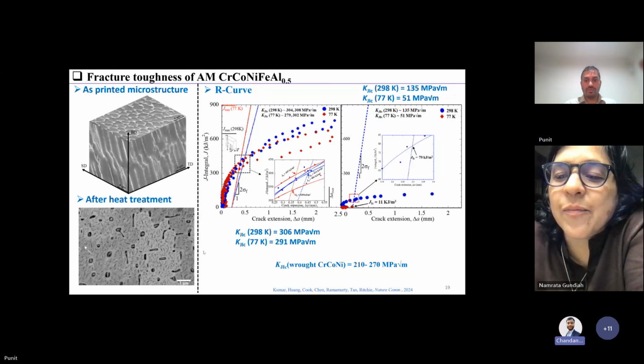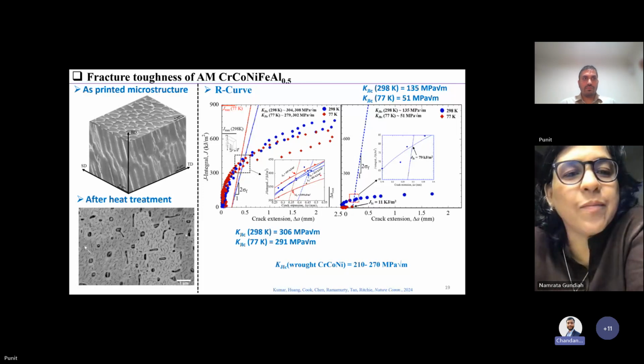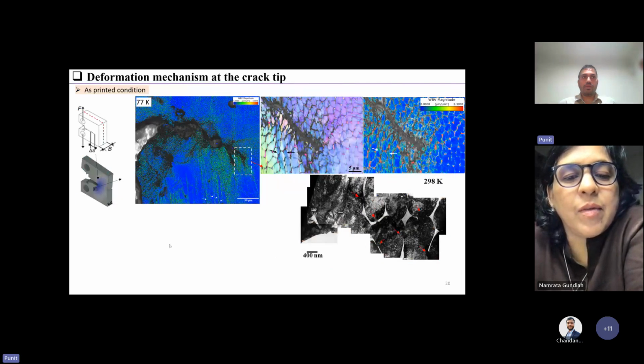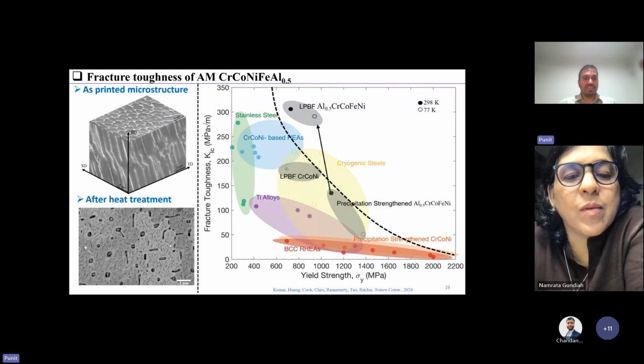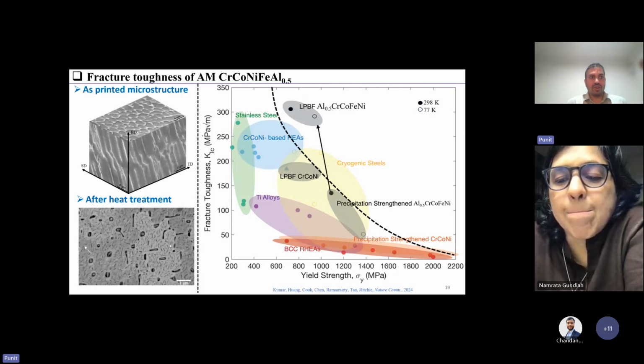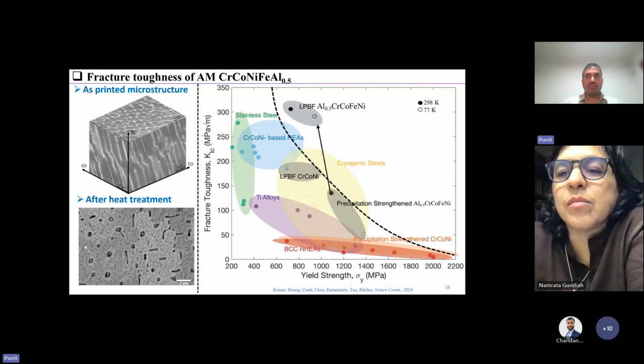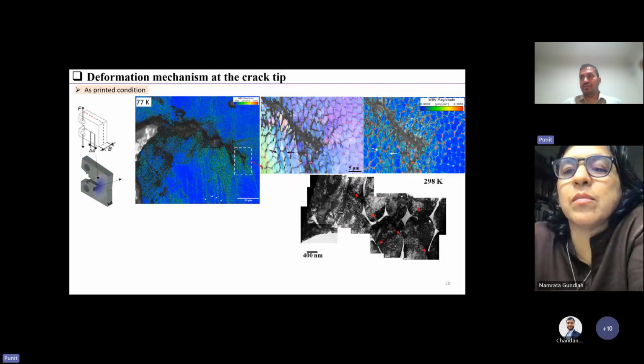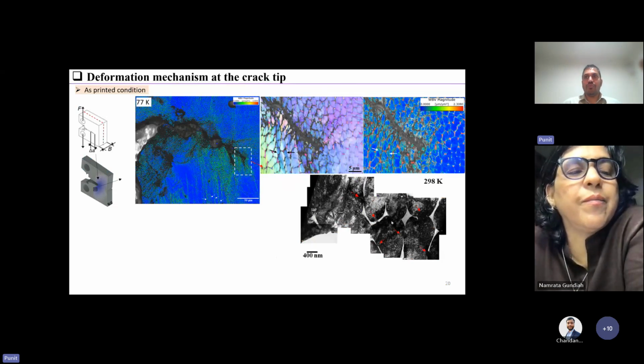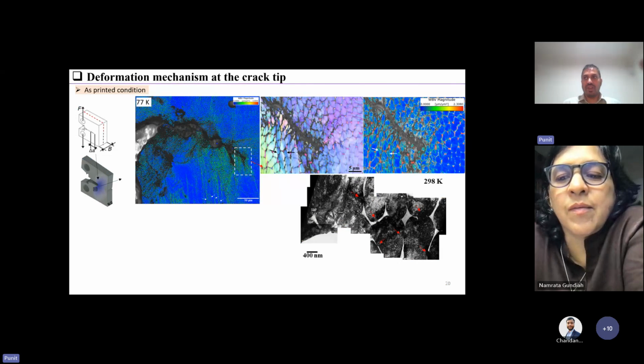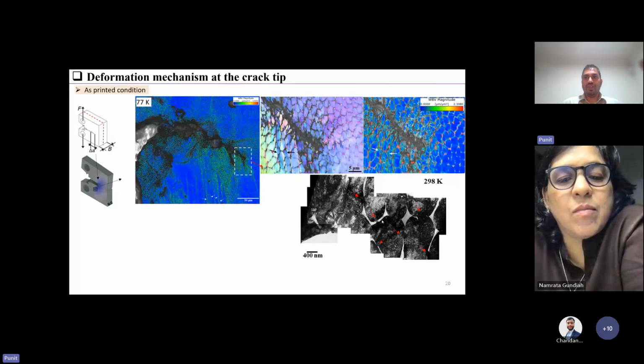I was asking, during the cryo test, the fractograph you have, it fails on the grain boundary, meaning at the B2 phase boundary. I don't think I've shown that. It doesn't fail on the B2 phase boundary. I haven't shown a fractograph. It doesn't fail on B2 because there is not a large difference between the strength of the B2 phase and the matrix. So the deformation mostly happens in the matrix, but we don't see such strain localization happening that the crack would nucleate on these boundaries. But that can happen.